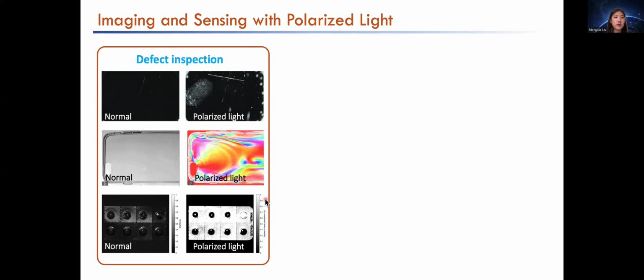Normal cameras are not very sensitive to contaminations or scratches that are generated during production. But polarized light is highly sensitive to the refractive index of the material. So if you get a fingerprint on top of a glass substrate, using polarized light, this thin layer of oil molecules can reflect the polarized light differently. So you will get a clear image of your fingerprint. This is how polarized light can inspect defects during manufacturing. This is the same for the scratches generated. And people can also use polarized light to identify a material or substance.